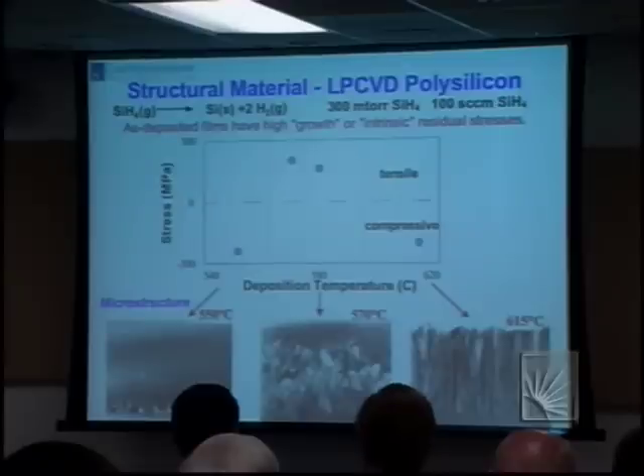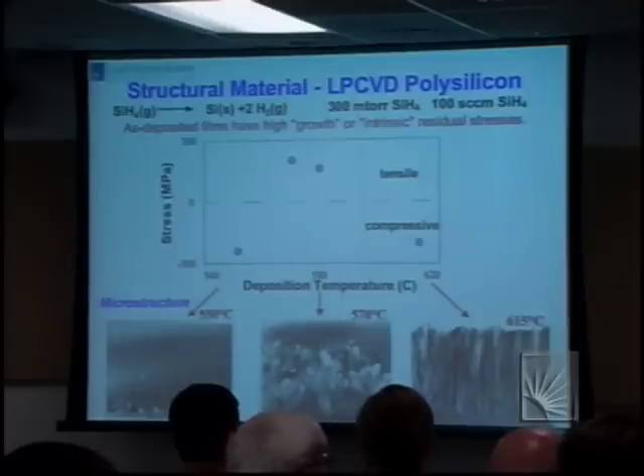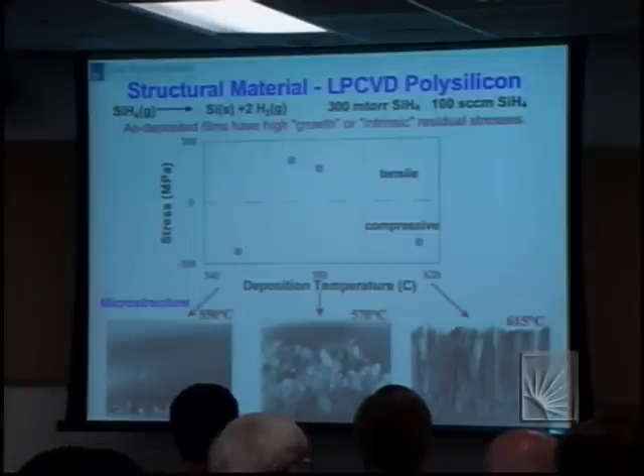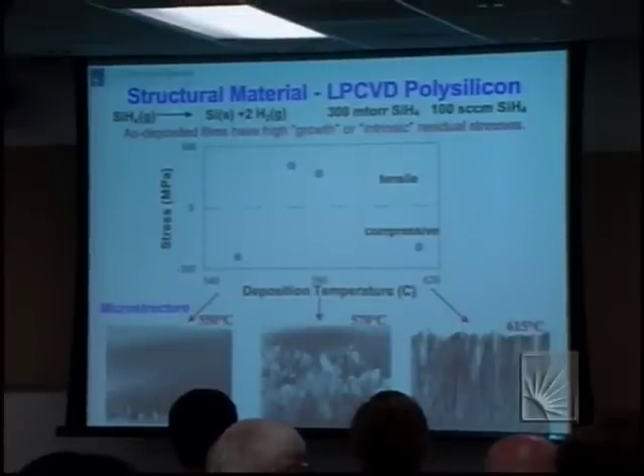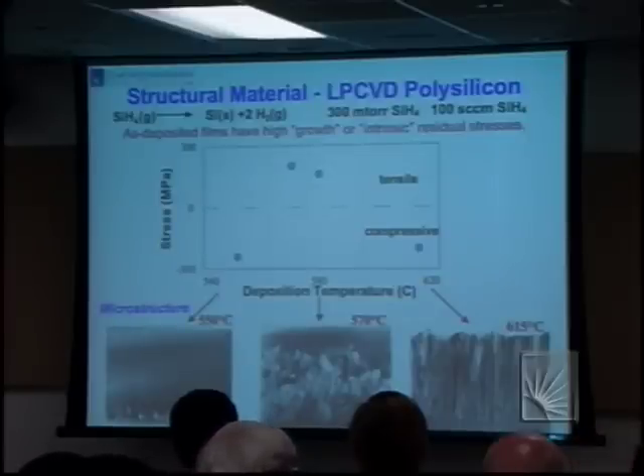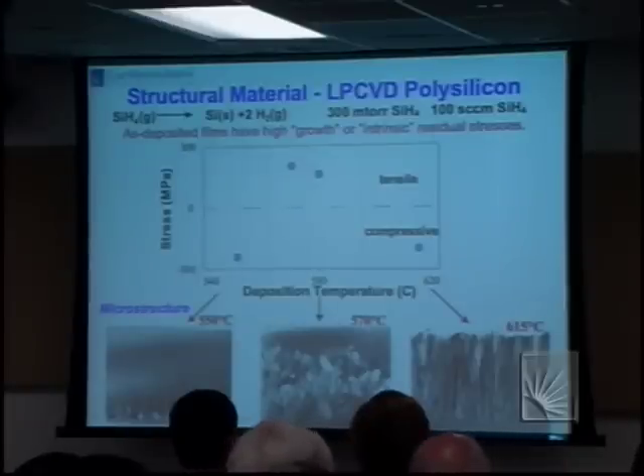It turns out that by the time you grow 5 microns of amorphous silicon, the first-formed material begins to crystallize. It's just a kinetic effect, and if you make a thinner film, you could get a purely amorphous material. You can see this at 570, where under the same growth conditions to allow a 5 micron film to be formed, about 80 or 90% of the film has crystallized. And by the time you get to 615, crystallization is essentially instantaneous. There is no or very small amorphous region, and you get a very familiar columnar microstructure. Very many CVD deposition processes give rise to columnar microstructures. Essentially, you limit nucleation, and whatever nucleates early just continues to grow.